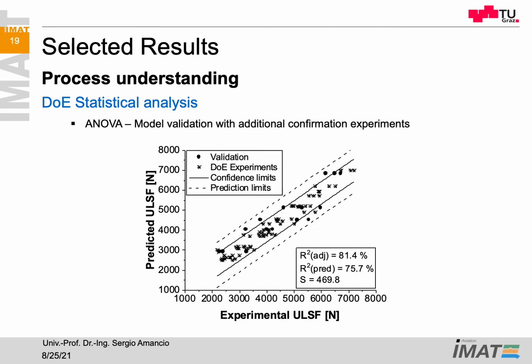Before we go through the analysis and process optimization, of course, we validated the model by producing additional validation runs marked in dark here. As you can see, there is a very good fitting of the model. So the adjusted R2 is 81.4, and the predicted R2 is 75.7, meaning that the model is very good to fit the data. So pretty much good for fitting the data in the range of analyzed factors or analyzed AddJoining parameters, and also has a fairly good prediction power of combination of process parameters that are outside of this range studied here.